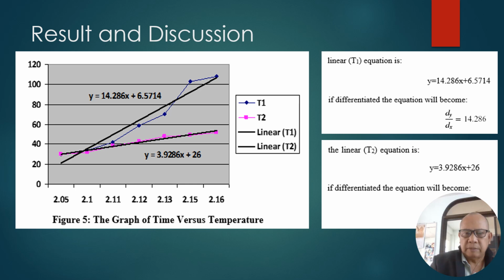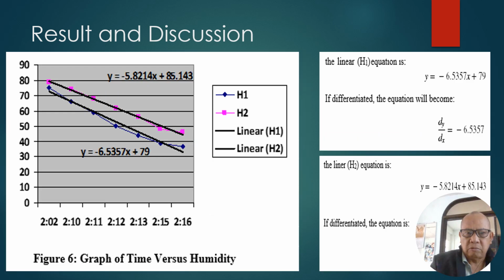Then the linear T sub 2 equation is y equals 3.9286x plus 26. If we differentiate, the equation becomes dy over dx equals 3.9286. So it shows that the increase in temperature for the portion of the furnace which is not covered by the coconut coir is higher as compared to that portion which is covered by the coconut coir.